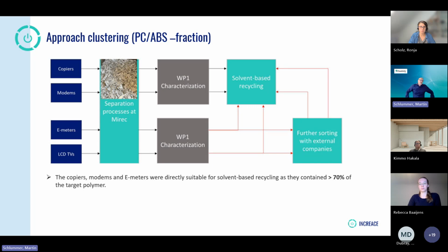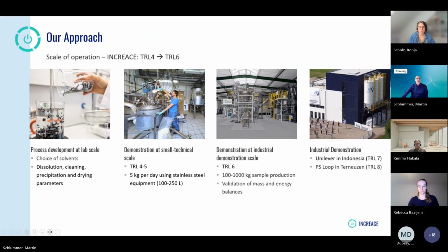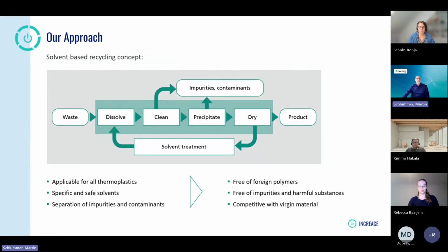Okay, great. Probably to take over from here, you see that one of the benefits of solvent-based recycling is that we do not need a 95 or whatever, 99 plus purity in the feedstock. We can make use of materials which have a purity of only 70% of the target polymer, which makes it easier to be implemented in existing lines without having, let's say, a severe additional effort from additional sorting instruments.